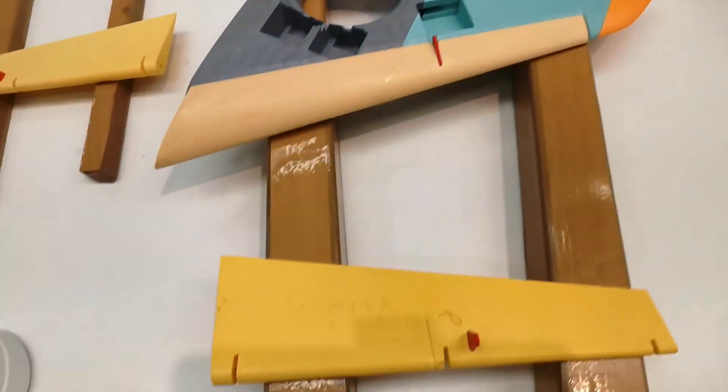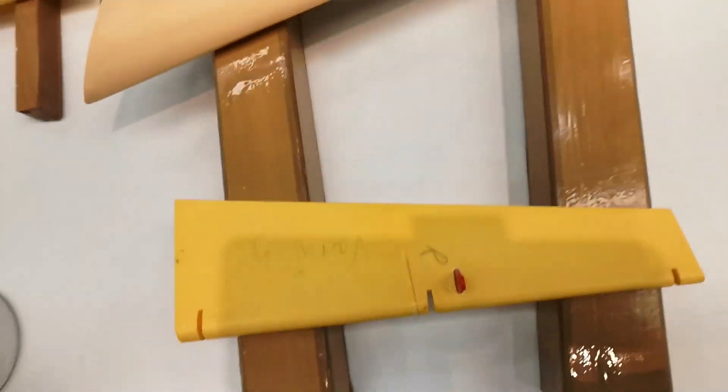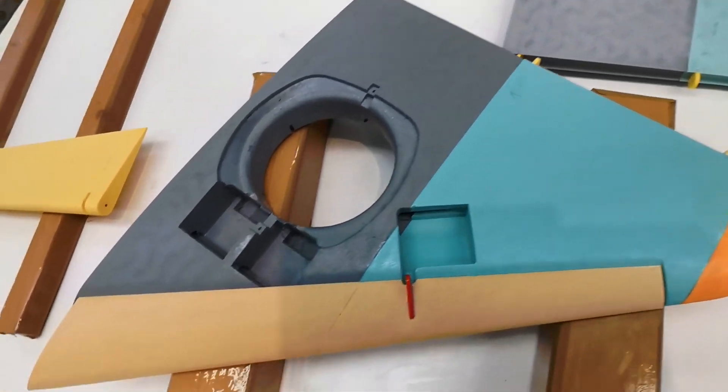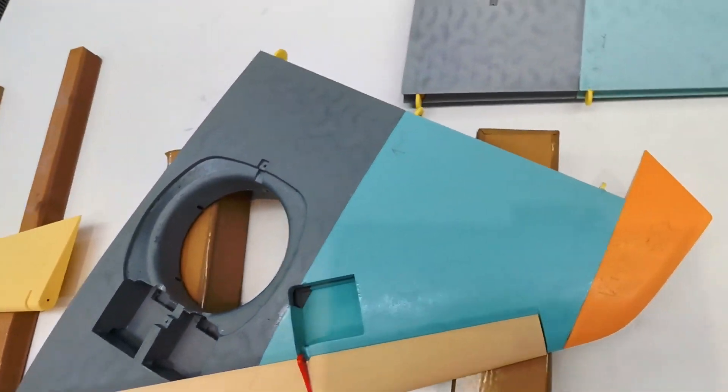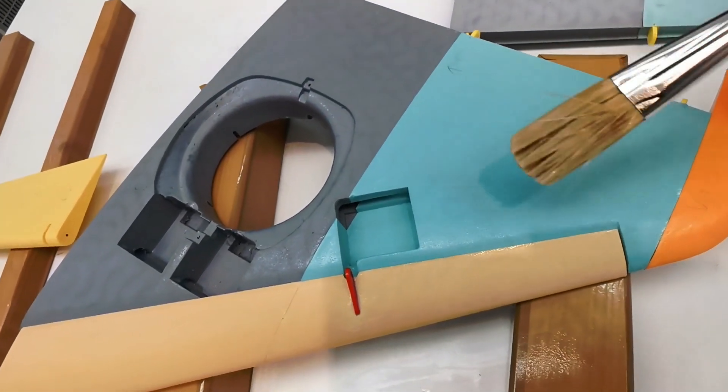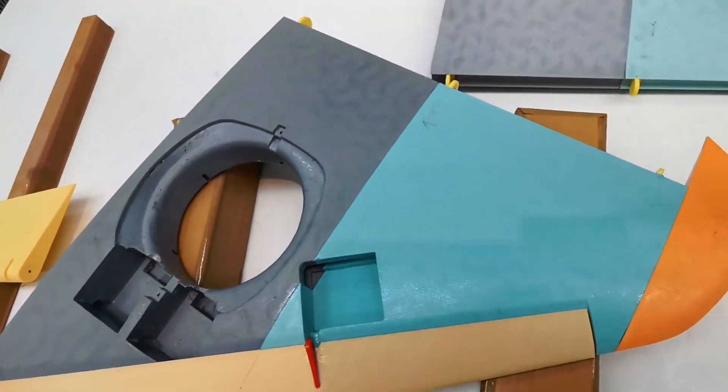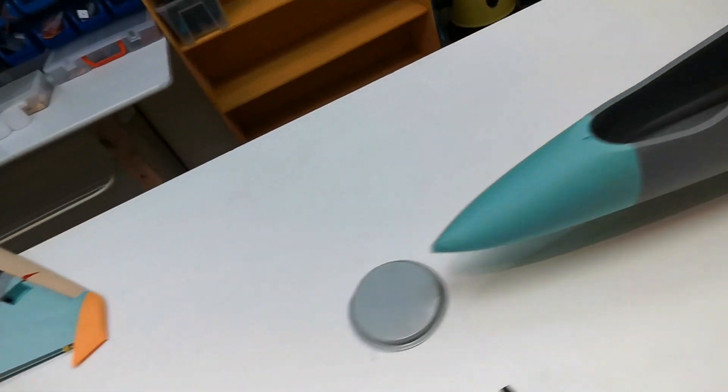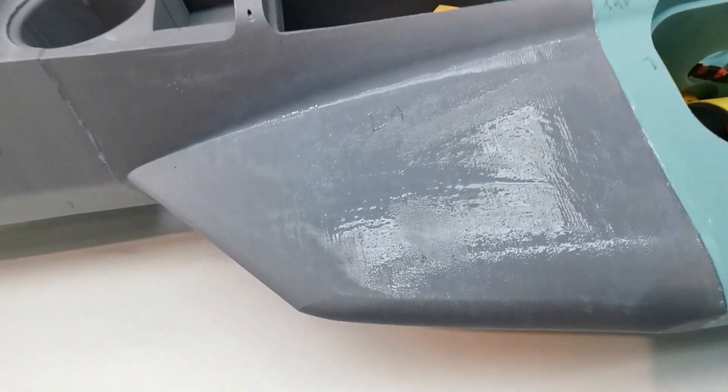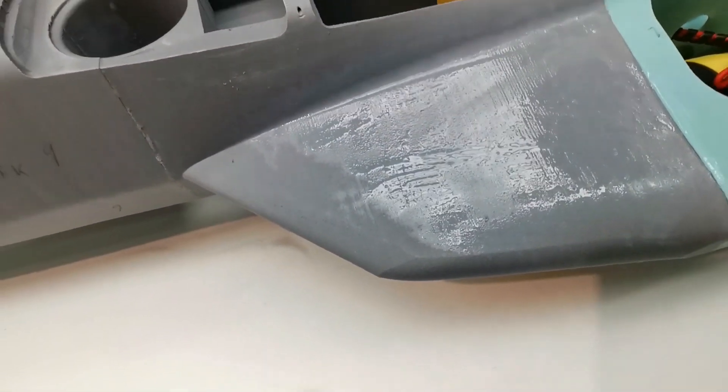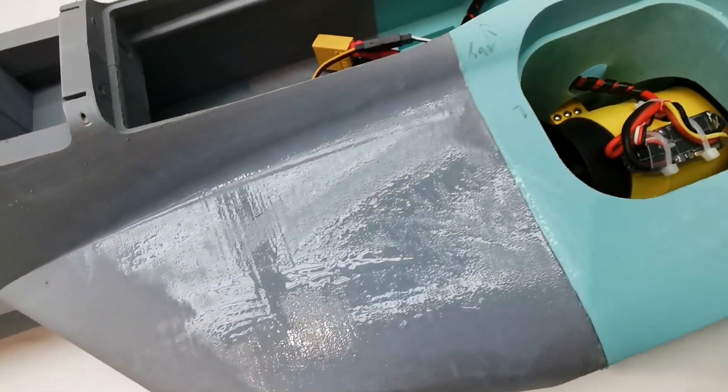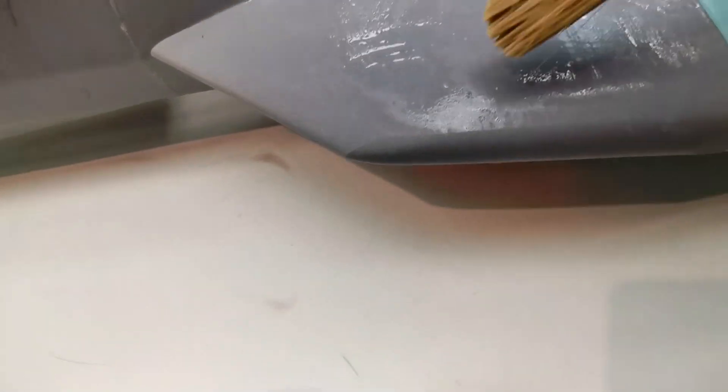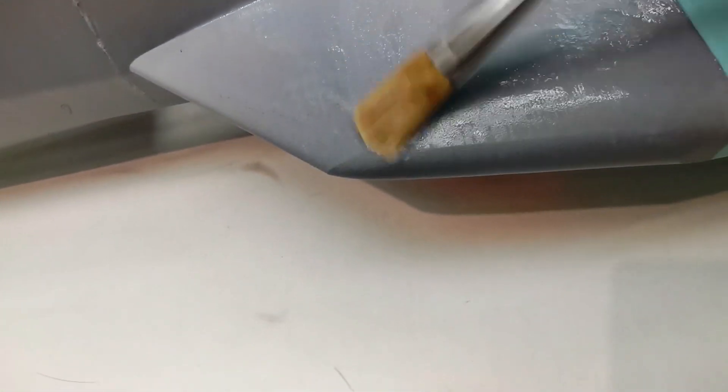Wing and elevator are done. You can see the surface looks nice, but they had been sanded right before. So the surface was opened and the varnish could suck into the surface. So this looks nice and clean. And here on the fuselage there was no sanding done, and the surface is closed. And it can't suck in and it stays on the surface, and this doesn't look so nice.